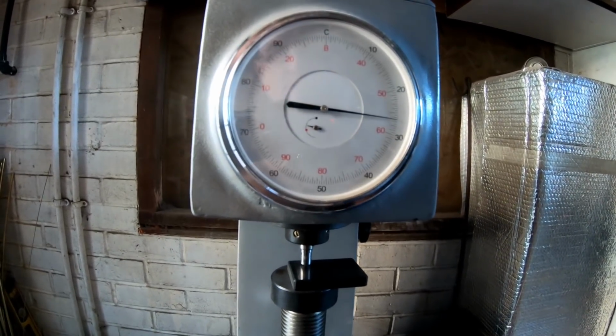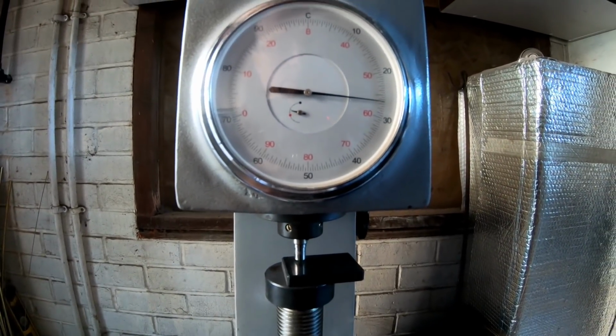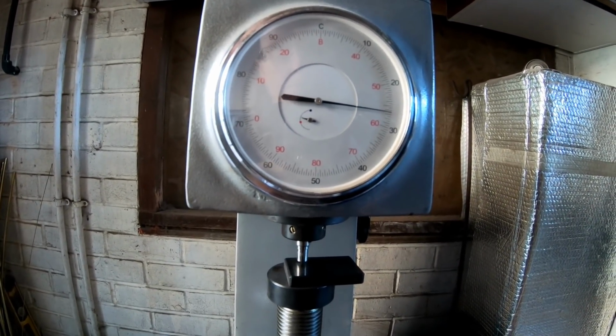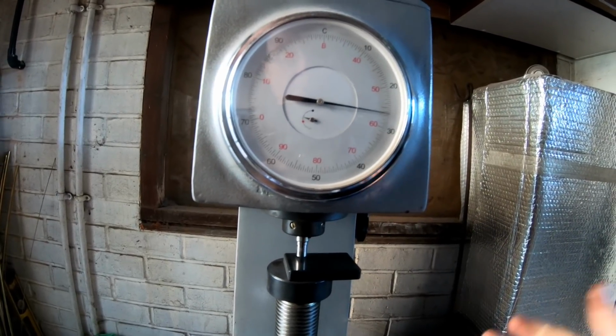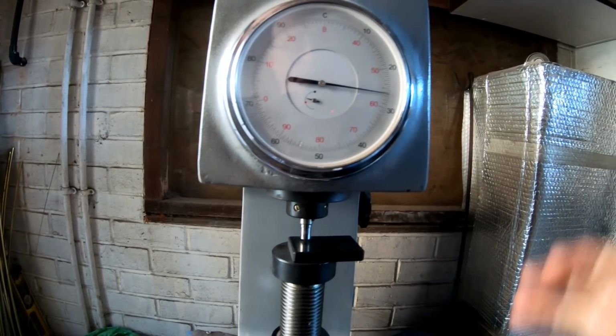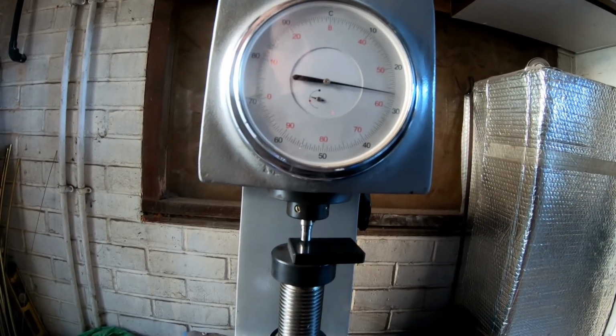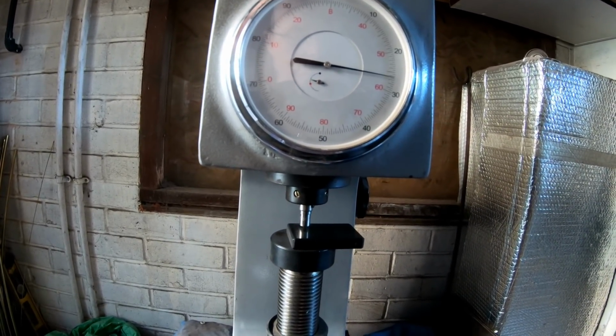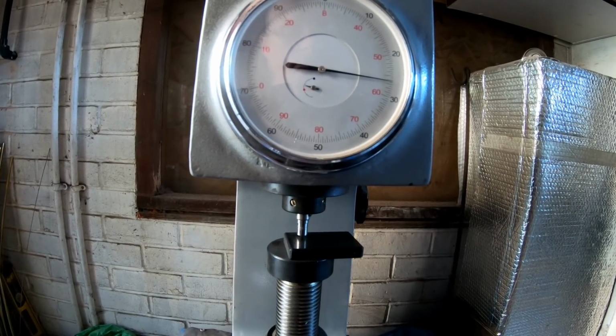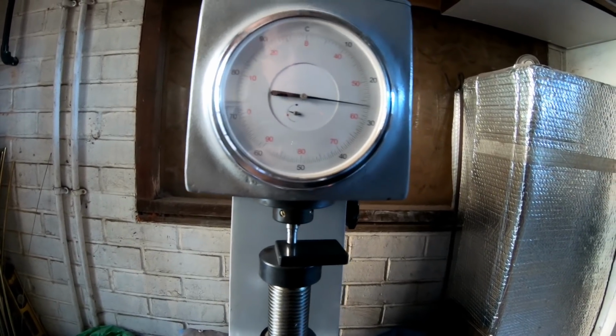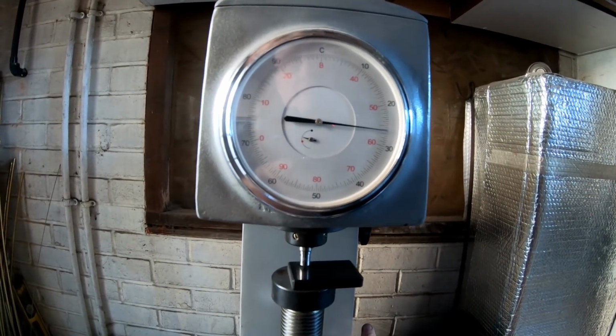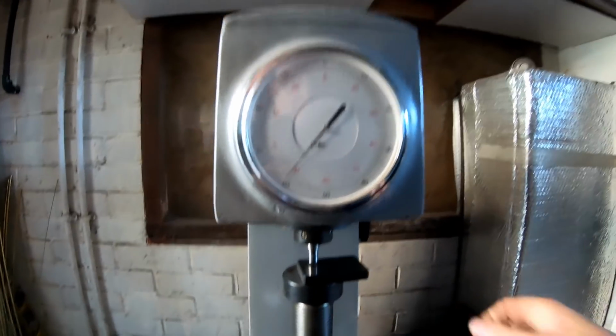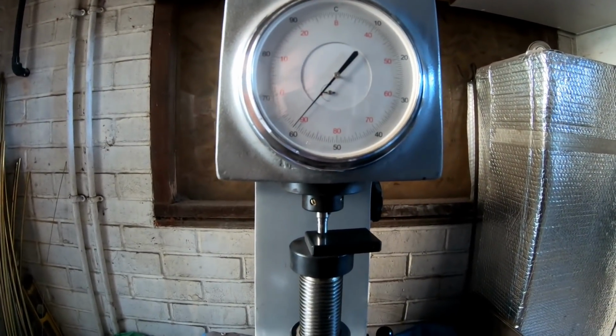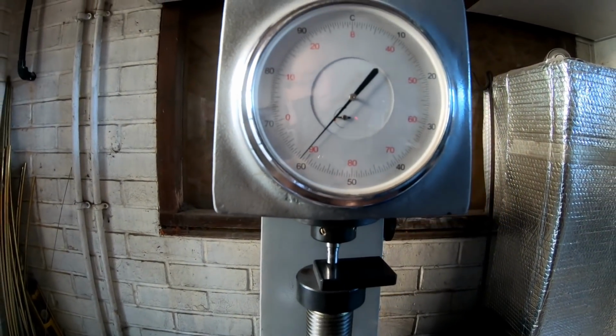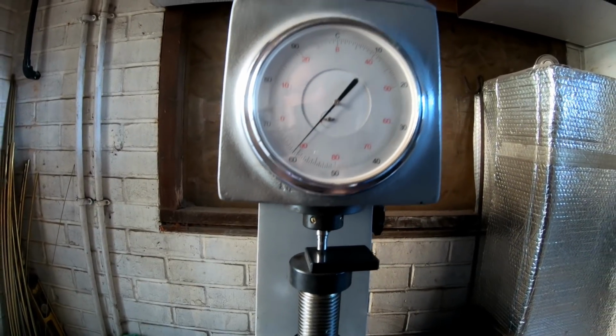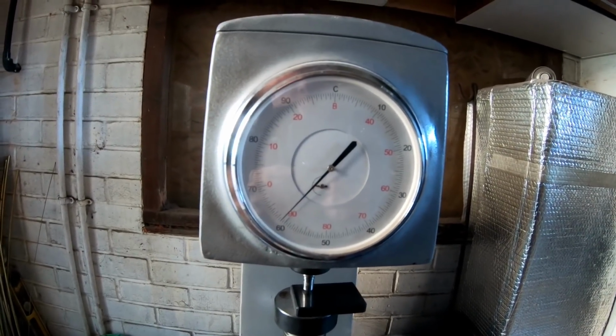And again, I go through the same process. It's important that you do exactly the same things that you do when you're measuring the blades as when you're measuring the block. You allow it to settle and leave it for the same amount of time. So let's see where we are with this. And we're 61. It's measuring 61, so I'm 0.1 of a Rockwell point out.